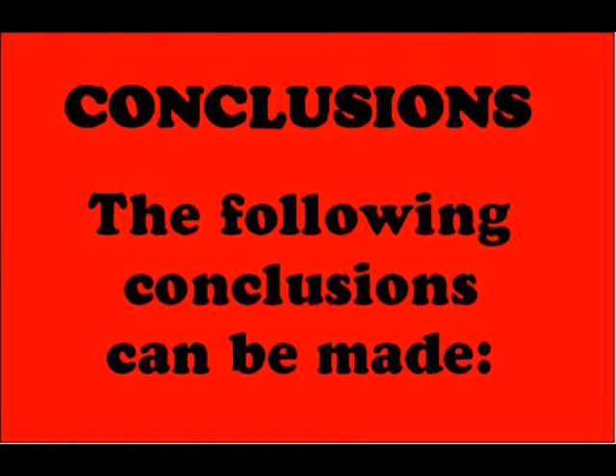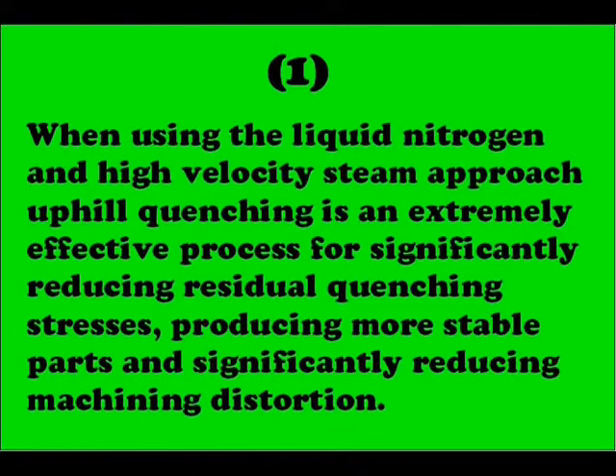Based on all technical data available and our over 30 years of research and experience with the process, the following conclusions can be made regarding the uphill quenching technique. When using the liquid nitrogen and high velocity steam approach, uphill quenching of high strength aluminum alloys is an effective process for significantly reducing residual quenching stresses, producing more stable parts, and significantly reducing machining distortion.